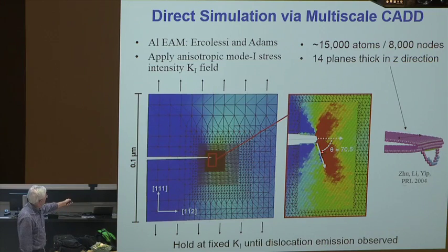In our method, the dislocation comes down, it gets passed as a continuum, and it sits in exactly the right place down here somewhere, but we don't have to have an atomistic description of it. It gives the right fields back to the tip, and all we need atomistically is to keep the tip. Right? So even in this very simple problem, because this dislocation has to sit out here somewhere, having the multiscale method is essential.